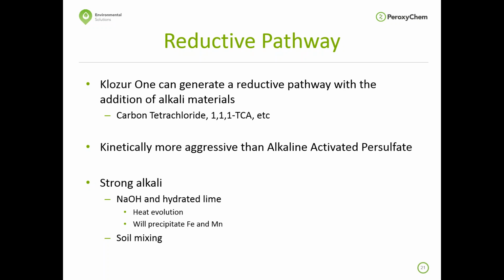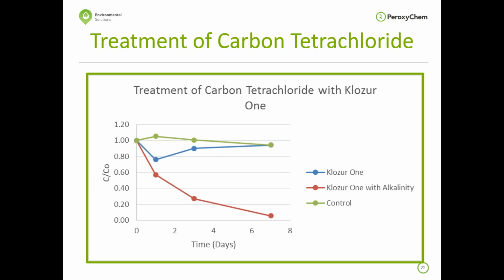Just to illustrate the reductive pathway, this is a slide showing the treatment of carbon tetrachloride. And the Klozur One, while it dipped down at the first time point, it basically moved back up, as we would expect it to be near the controls after 3 and 7 days. Whereas with the Klozur One with alkalinity, the carbon tetrachloride continues to decrease. This study was run at a relatively low pH, a pH of about 10, 10.5. But what we saw with increasing pH, say if you were to get the pH of around 12 or so, the kinetics were even faster with Klozur One.